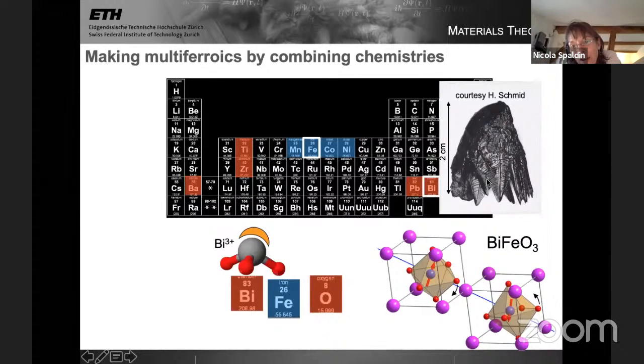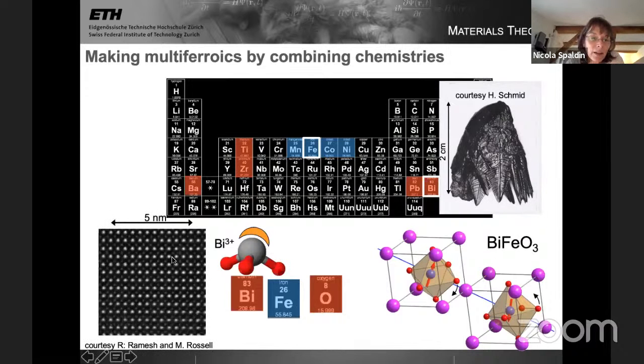These striations that you see here are the result of twinning, and the black color is because it really has a lot of defects. And so this was a beautiful sample of bismuth ferrite, but it was not possible to demonstrate in this sample that it was actually multiferroic. For example, ferroelectric switching could not be achieved. So in the early 2000s, the real breakthrough came from abilities in synthesis, and in particular in thin film growth.